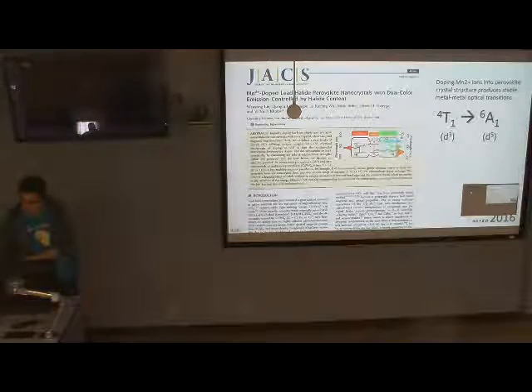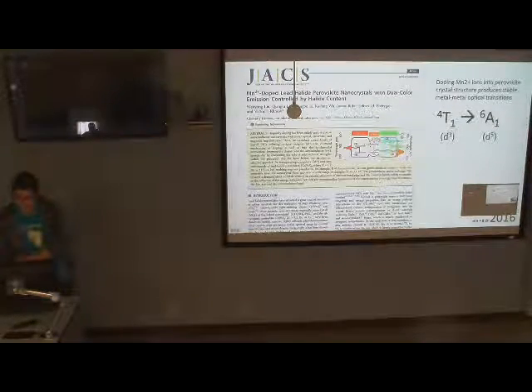And then through their analysis, they characterized the emission from the Mn2+ ion as a T1 to A1 transition, so it's basically a spin flip. So it starts in the excited state. After photoexcitation, you have non-radiative relaxation from the conduction band of the perovskite to the Mn dopant. And then through a spin flip process, you can get emission out of them.